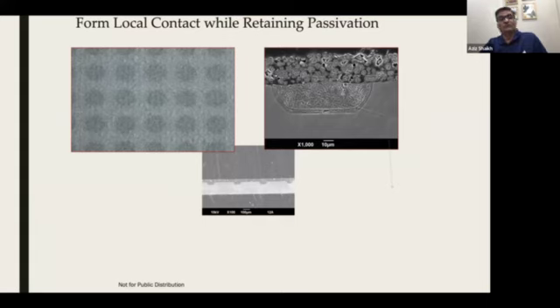This shows an SEM picture. You can see here this is the backside of the cell. This gray is aluminum, and the dark gray is where the passivation is open. Wherever the passivation is open, you see that it has reacted and formed this cup. Inside the cup, there is aluminum silicon alloy, and this ring here is the BSF. So you have BSF as well as passivation. This is the PERC technique, and it is a highly successful technology today, though it is being transitioned out to newer technology.